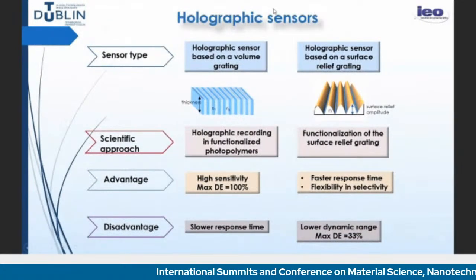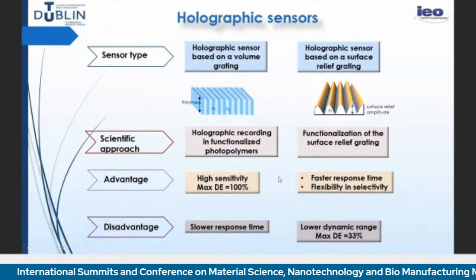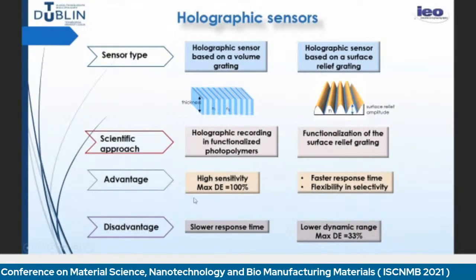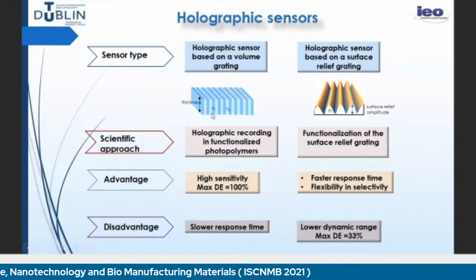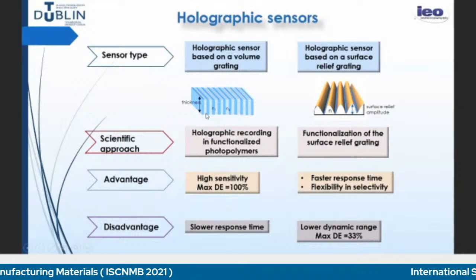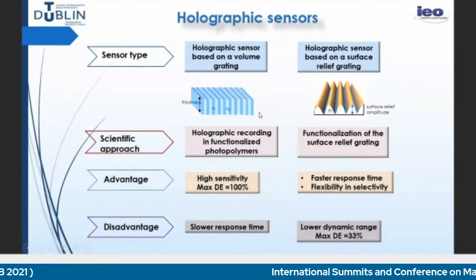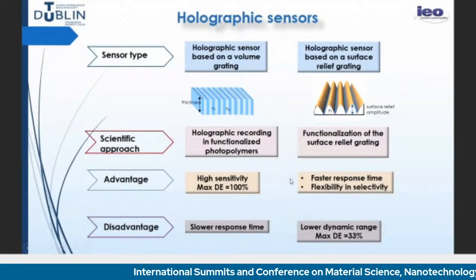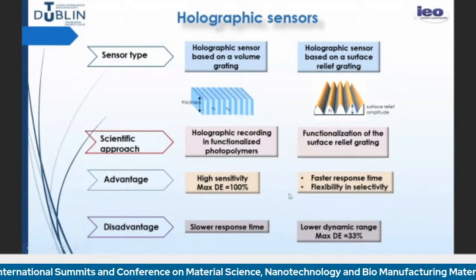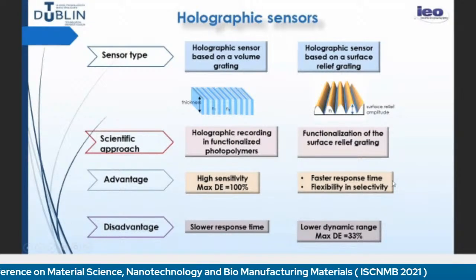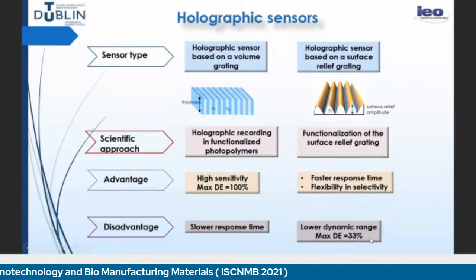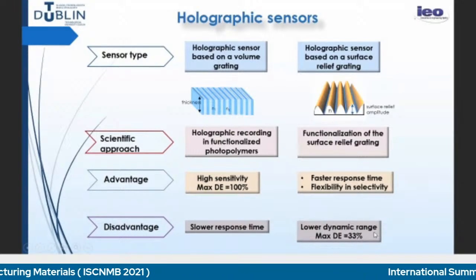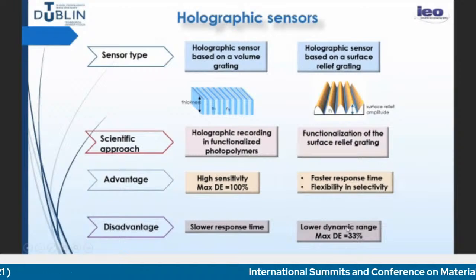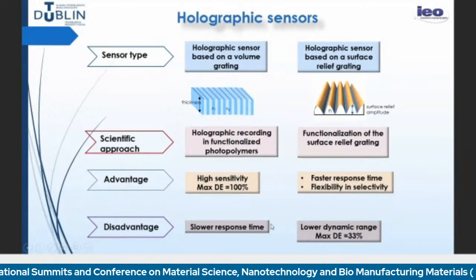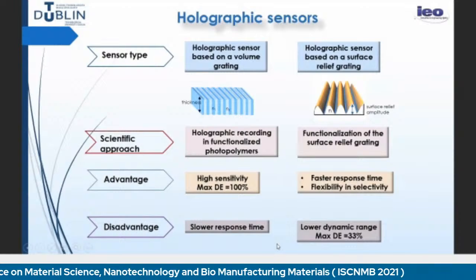So we use two types of sensors, as I said, the volume sensors and the surface sensors. The main advantage of the volume sensors is that they are very sensitive, because the optical path of the beam is much larger. So even a small change in the properties will be accumulated in a phase change, because the beam travels longer through the material, and the maximum theoretical diffraction efficiency is 100%. Surface gratings are faster in response time and flexible in terms of coatings, but their dynamic range is smaller. Typically, for a sinusoidal grating, the maximum diffraction efficiency is 33%. Of course, for the volume gratings, the response time is slower, because the molecules need to diffuse over longer distances.